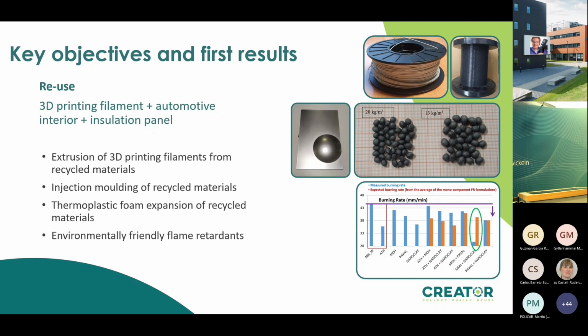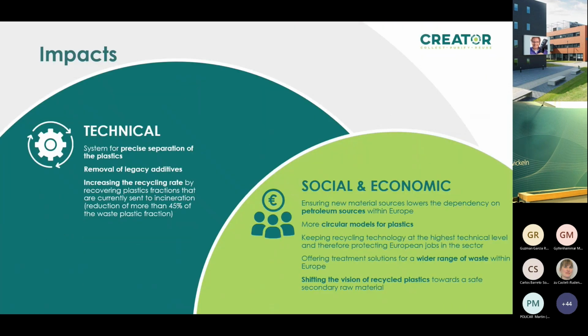The 3 different demonstrators were produced without the flame retardants, and depending on the application, new environmentally friendly flame retardants were potentially added, showing the same burning behavior as what we had seen before with the added HBCD flame retardants. So we could prove that similar properties could be obtained after purification of those recycled materials and after adding some new environmentally friendly flame retardants, similar to the materials before recycling. So I think this is a very nice result: purified, REACH-compliant recycled materials that could be used.